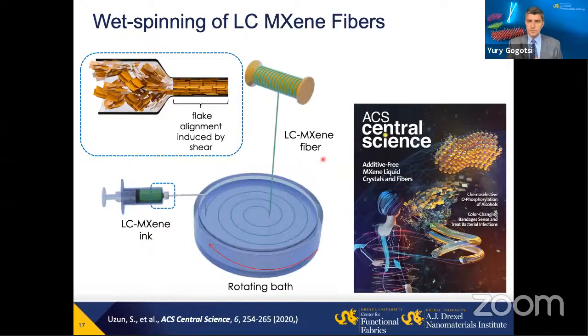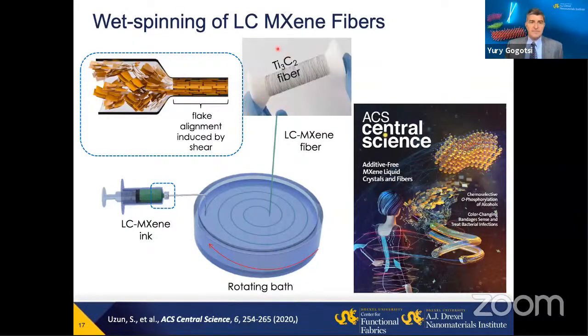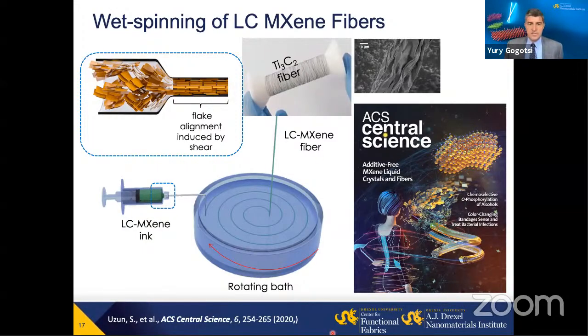Moreover, since those are two-dimensional sheets, they can, just like graphene oxide, form liquid crystal. And we can produce films. We can also even pull fibers from a liquid crystalline MXene, making pure MXene fiber. There are probably 5 meters, if I recall correctly, on this spool of titanium carbide Ti3C2 fiber, which is again just MXene. This is an SEM image showing the surface of this fiber here.